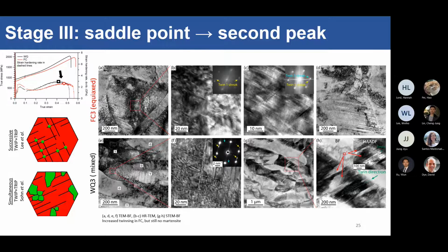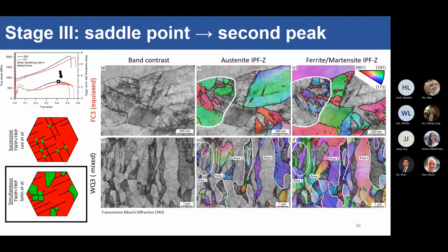In another austenite grain here, we can see that you've got some martensite. These in the bright is the martensite going across the austenite lath here as well. So I think at this point it's safe to say that our steel, both of these steels actually, deforming by the simultaneous TWIP plus TRIP mechanism because we couldn't find any martensite at any of the twin intersections in this steel. Right, so we've been paying attention to the twins.